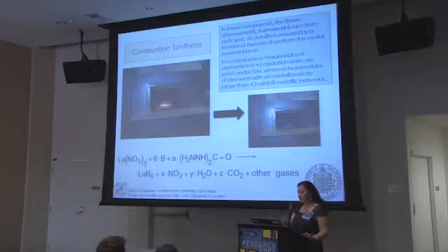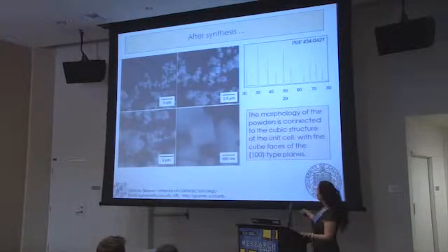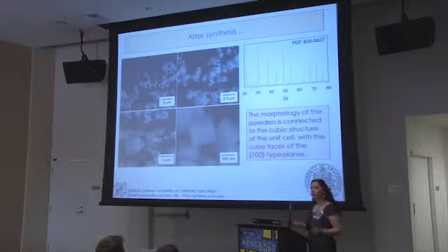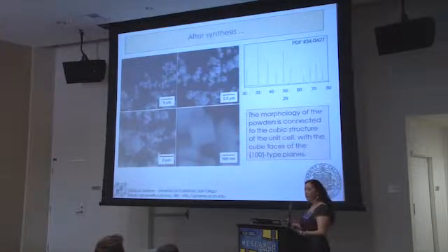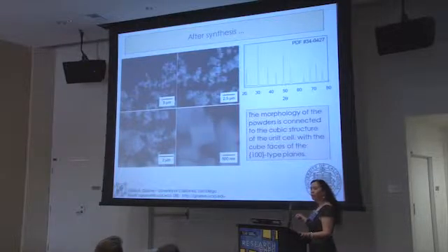After the synthesis, as I told you, we get this very nice powder. They do have a little bit of oxide on the surface, lanthanum borate, in fact, and we need to clean that up. And so this is the concept of controlling morphology by acid cleaning. In this case, the material wants to, in fact, be in the form of cubes because that's the crystal structure.